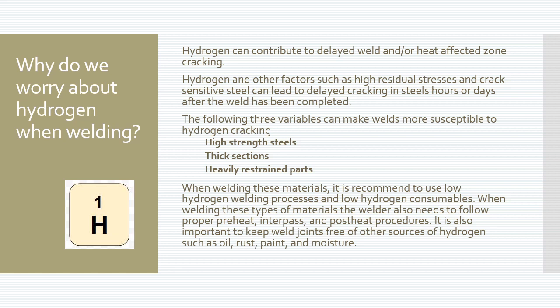The following three variables can make welds more susceptible to hydrogen cracking: high-strength steels, thick sections, and heavily restrained parts. When welding these materials, it is recommended to use low hydrogen welding processes and low hydrogen consumables. The welder also needs to follow proper preheat, interpass, and post-heat procedures. It is also important to keep the weld joints free of other sources of hydrogen such as oil, rust, paint, and moisture.